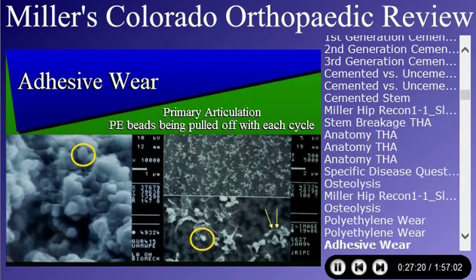And if you look even closer, you see these little tails. And what is happening is that these beads are literally being pulled off. It's adhesive wear. As that bearing ball comes through, it literally pulls those beads off. And that is adhesive wear. And those are submicron in size. That SEM has a 1 micron bar there, so those particles are about a half micron in size. And you're generating billions and billions of particles over the life of that prosthesis.